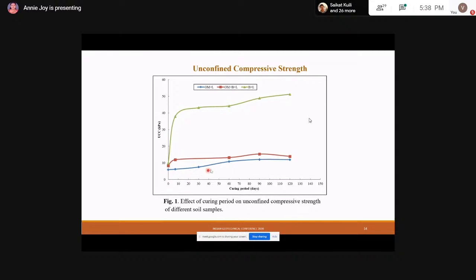Similarly, when you consider the blue curve, that is for the organic matter plus lime, here also you could see a similar trend, like an increase in strength up to 90 days and then a decrease. And here we could observe a decrease in UCS strength of about 77% when compared to that of bentonite lime at the end of 120 days.